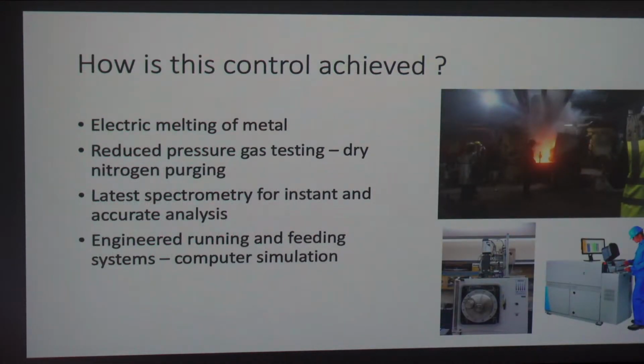So, how is this control achieved? Well, the first thing to say is all of our metal is melted electrically, in induction furnaces, so you don't have the propensity to absorb gases from the fossil fuels that you'd use to melt metal, because it's a completely inert environment. We can do reduced pressure gas testing, because we take a little sample and put it under reduced pressure and you can see if there's dissolved gas in the metal, because it will spit, and you can make sure by purging. We use dry nitrogen purging, which takes the gas content right down to very little.